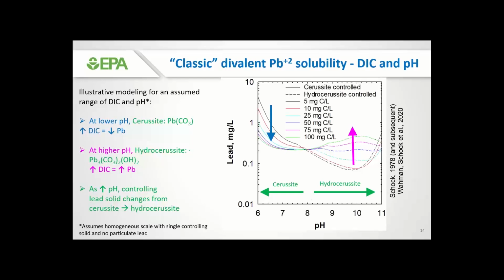This again is an illustrative solubility modeling diagram for an assumed range of dissolved inorganic carbon and pH. So you see here different curves representing a DIC of 5 milligrams per liter of carbon all the way to 100 milligrams per liter of carbon. And you can kind of see two general areas on the graph at low pHs. So toward the left area of the graph, we have one set of curves here where the higher the DIC, the lower the lead leaching.